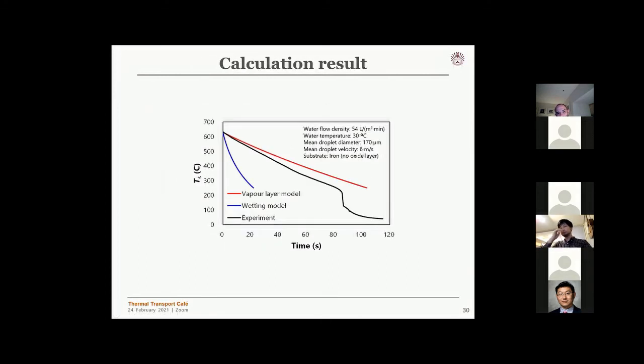Okay, so this is just recently we got done. We now plot this temperature profile as a function of time. As a reference, I plotted here the black line. This is a cooling curve obtained by our experiment. And this red curve is the cooling curve predicted by our model, just presented.